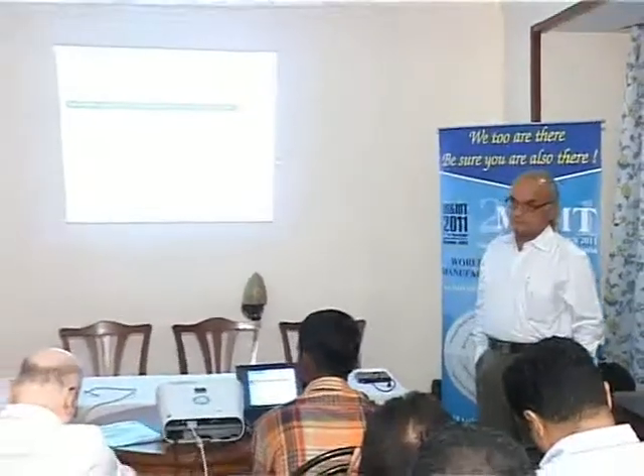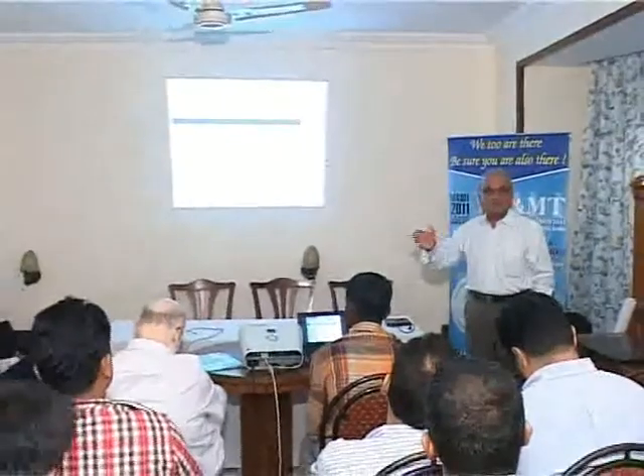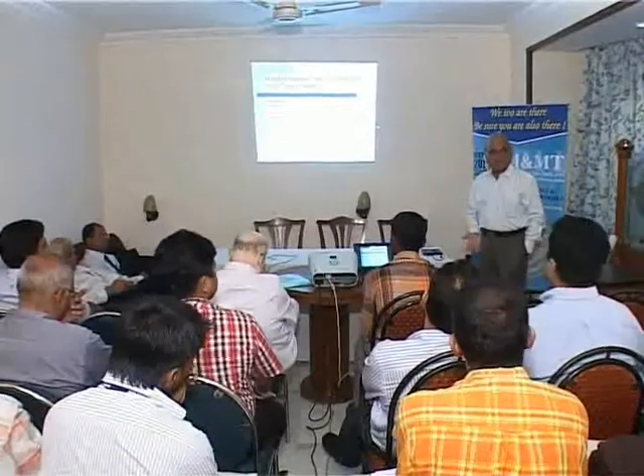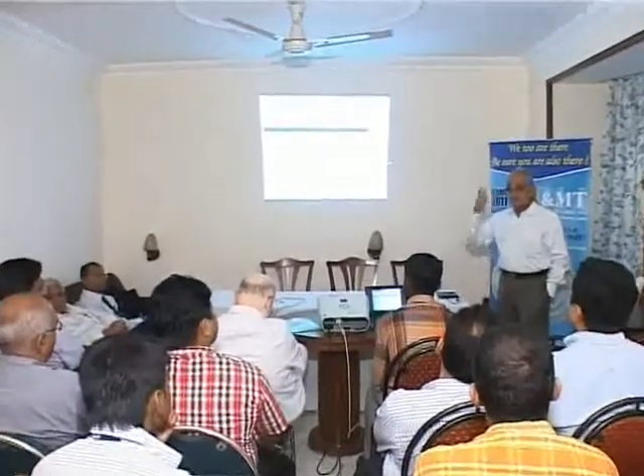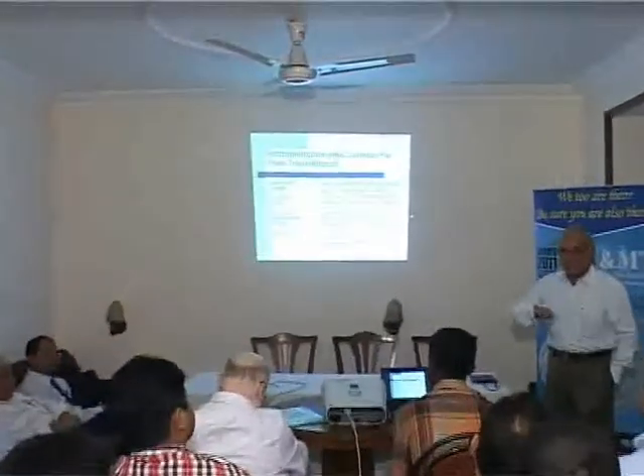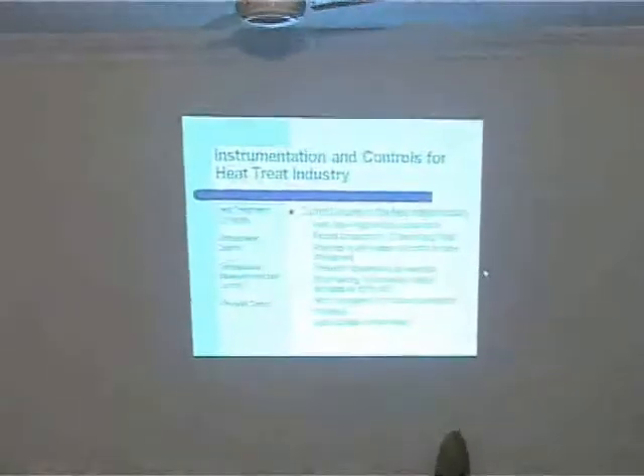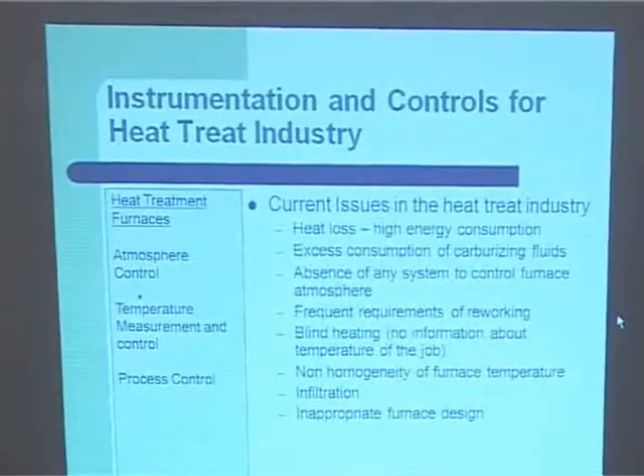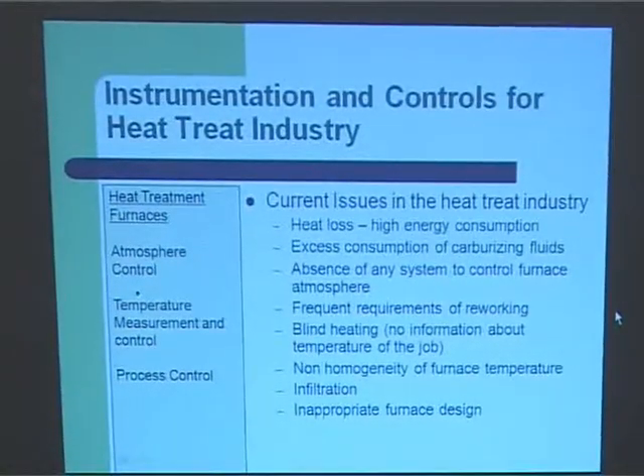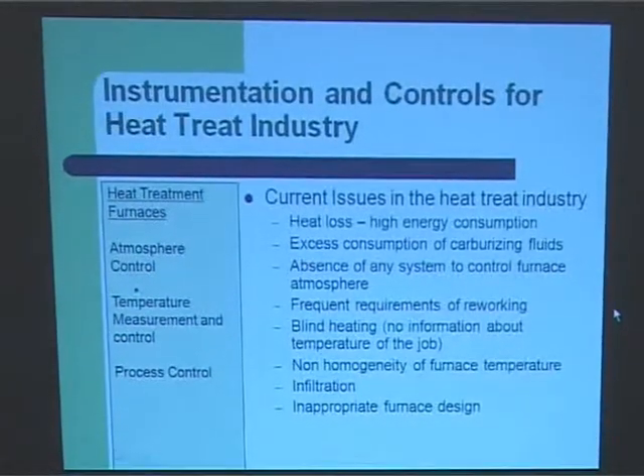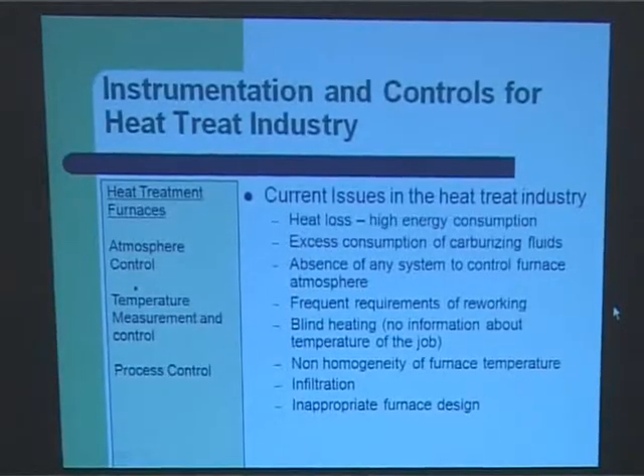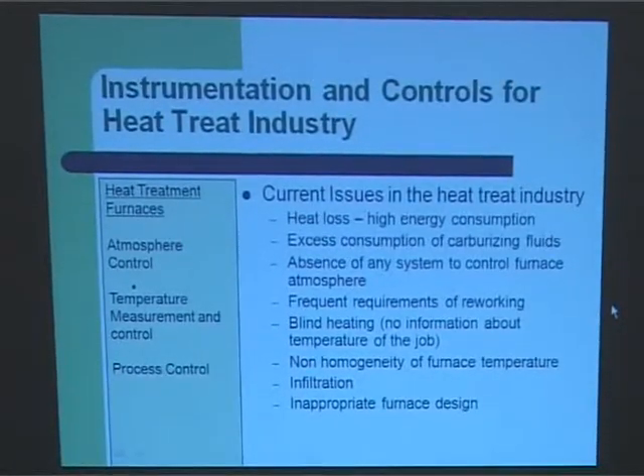And this is another factor which we find in the Indian furnaces, especially pit type furnaces. Pit type furnaces are invariably two-zone heating, top and bottom. There are bigger furnaces with three-zone heating, top, middle and bottom. And there is a faithful fan on the top of it, no doubt. But despite the convection current, are you sure your temperature is homogeneous throughout the range? If not, some jobs get over-carburized, some jobs get under-carburized. This is where you have to pay attention to the furnace design as well as the homogeneity of the furnace. Next.